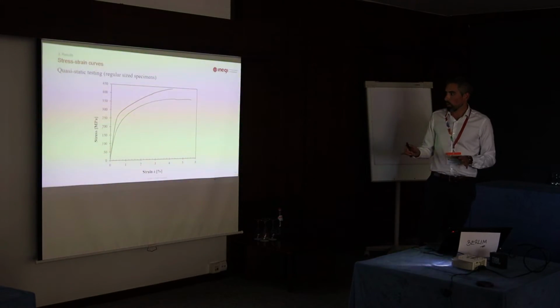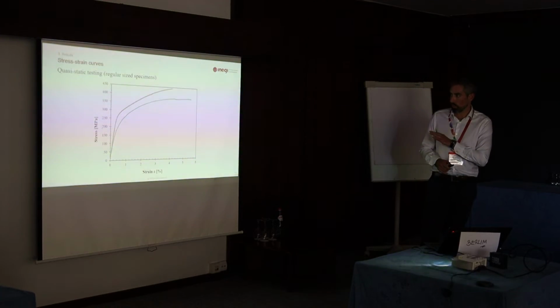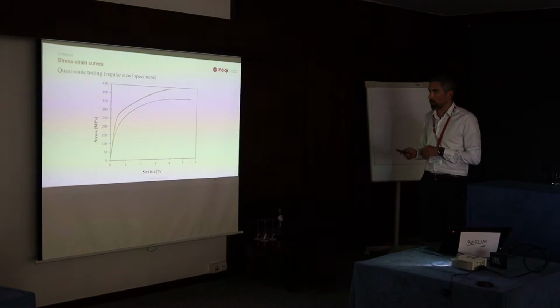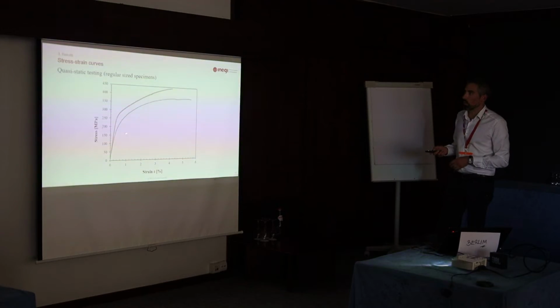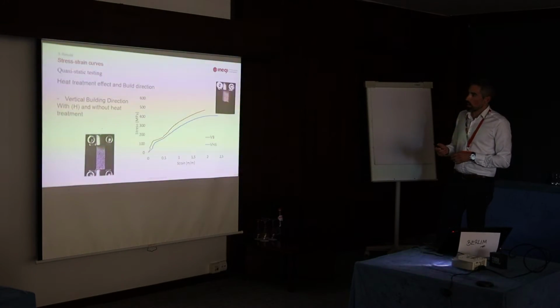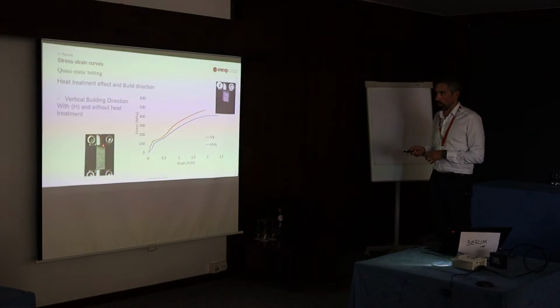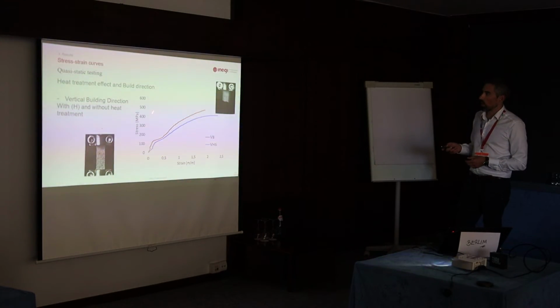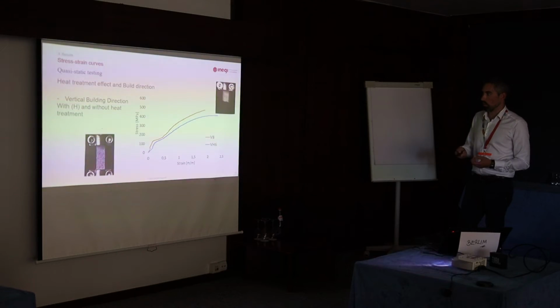Here, for a normal-sized specimen produced, we could see already the expected effect of the heat-treated specimen versus the non-heat-treated specimen. These are already micro-flat tensile specimens. This one is the heat-treated specimen. We can see again the expected behavior, the influence on the material. This was the vertical build direction, so basically up from the powder bed surface.